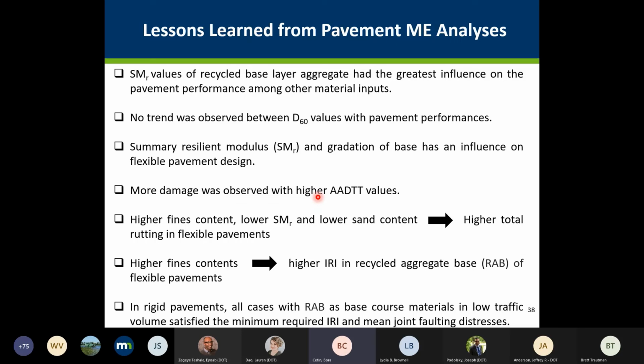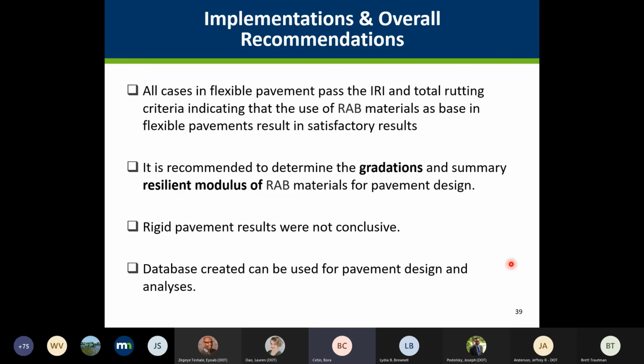And higher fines content, like I said, for flexible pavements, we were clear. With higher fines content, it ends up with lower resilient modulus value, and with lower sand content, which resulted in higher total rutting. And higher fines content resulted in higher IRI in recycled aggregate base of flexible pavements. And in rigid pavements, again, like I showed, all cases with these recycled aggregate bases as a base course material in low traffic volume satisfied the minimum required IRI and mean joint faulting distresses, but with medium and higher traffic, the results were inconclusive.